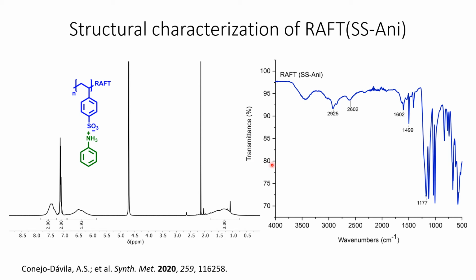To complement the elucidation, we use FTIR spectroscopy. The spectrum shows the band of the nitrogen-hydrogen bond of the anilinium ion. Also, we can observe the classic bands of the carbon double bond carbon of the aromatic system. Also, the stretching of sulfur-oxygen came from the sulfonate substituent. Based on this, we can confirm the formation of the macro-RAFT agent.